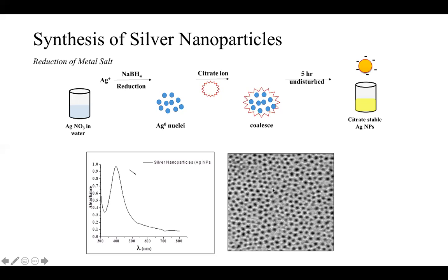To support that as well, we use a TEM image, which is just transmission electron microscopy, to kind of show that our particles were dispersed in size and uniformity, that can be used as a stable method of nanoparticles to be used and studied for research.